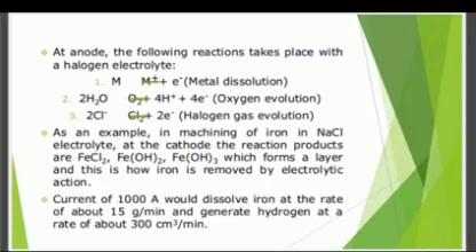As an example, in machining of iron in NaCl electrolyte, the reaction products are FeCl2, Fe(OH)2, Fe(OH)3, which form a layer, and this is how iron is removed by electrolytic action. A current of 1000 ampere would dissolve iron at the rate of about 15 gram per minute and generate hydrogen at a rate of about 300 cubic centimeter per minute.